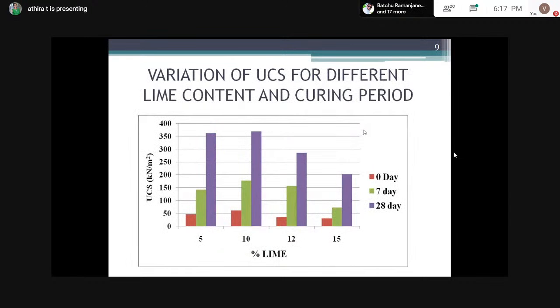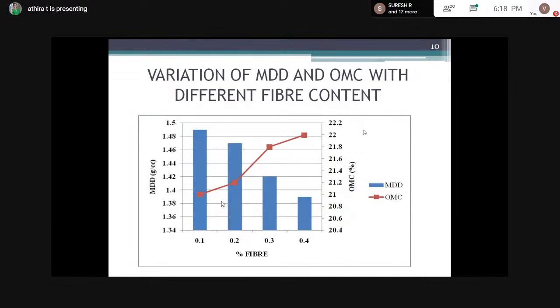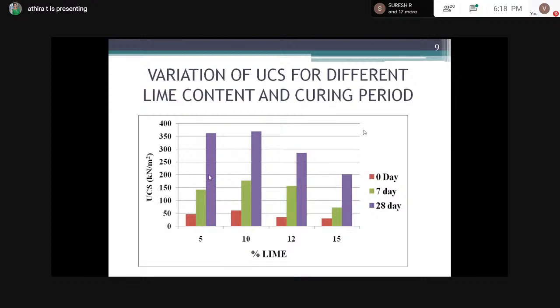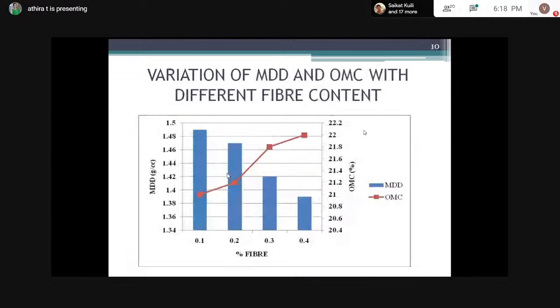Now, by getting the optimum moisture content, we are conducting the unconfined compression test for different dosages of lime. As we can see, up to 10%, the UCS shows an increase in value, but with further increase in the lime, it shows a decreasing trend. And also by comparing the different curing periods, we can see that maximum strength was obtained for the sample cured for 28 days. And here we get that 10% of the lime was obtained as optimum percentage.